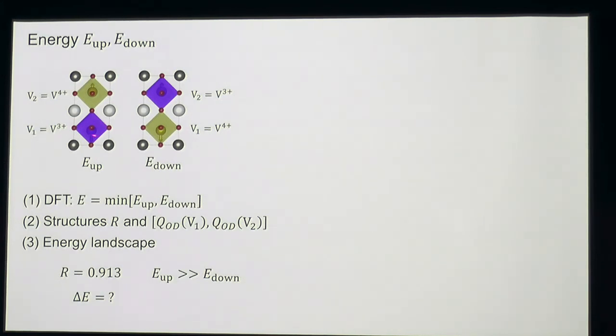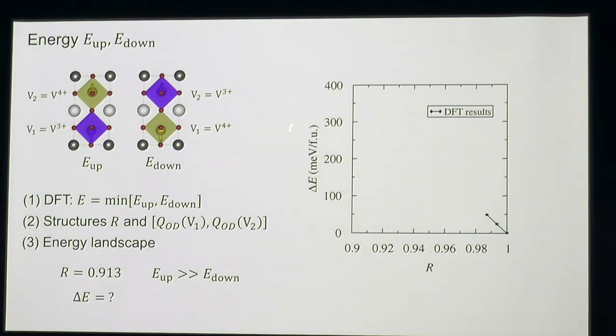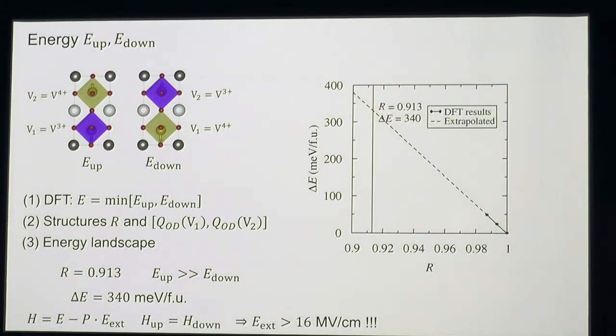If we put the extra electron in the vanadium, it will automatically go to the other vanadium. As a result, we cannot calculate the energy difference between the two electronic states directly, but we can estimate this value according to the values we have. We plot the energy difference between the two polarized states for R values close to 1. Then we extrapolate the line, and from the intersection with the line corresponding to R equal to the optimized value, we estimate the energy difference, which is 340 meV per formula unit, which is quite large. In order to induce such a polarization flipping, such a big energy difference should be compensated, which requires an electric field larger than 16 MV per centimeter, which is unrealistic.